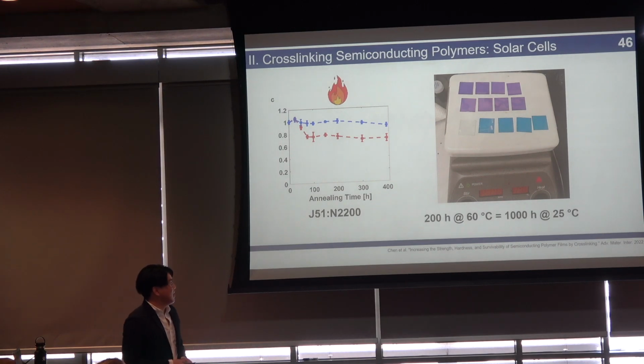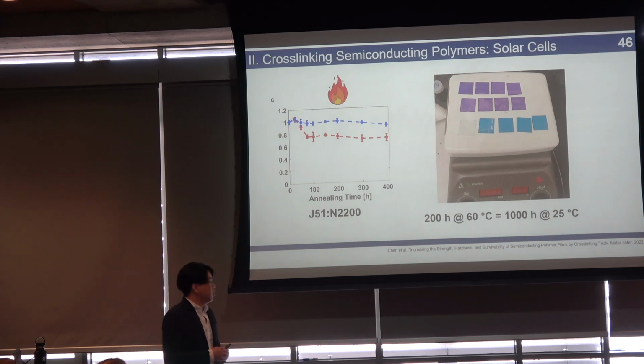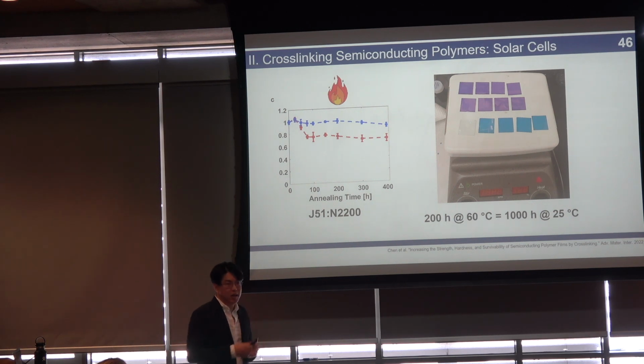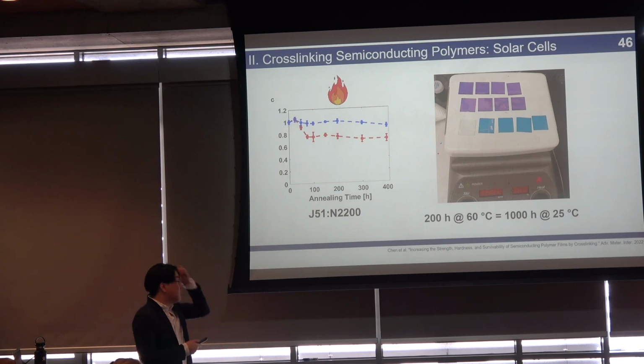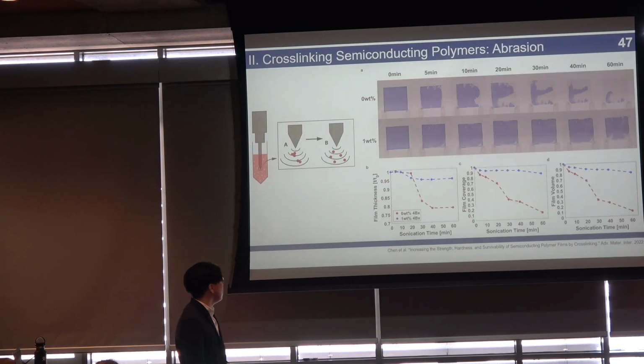So 200 hours at 60 degrees Celsius, assuming degradation occurs with an Arrhenius function, corresponds to a stability of about 1,000 hours at 25 degrees Celsius.